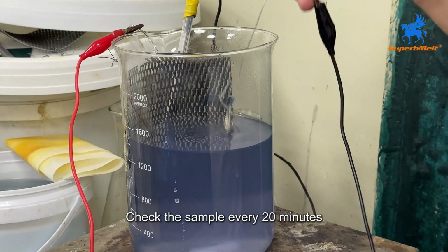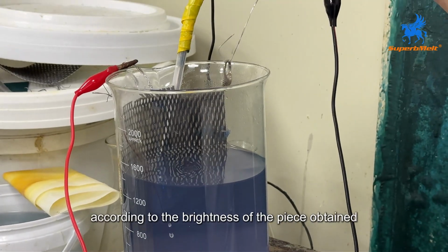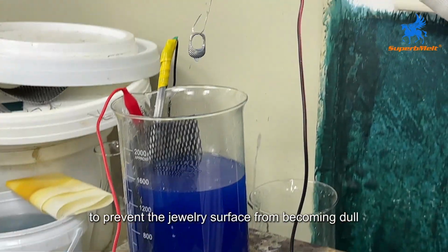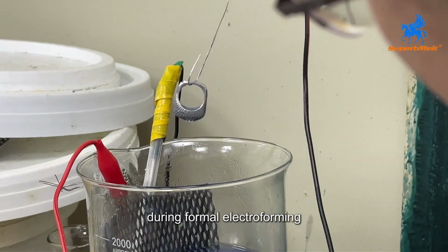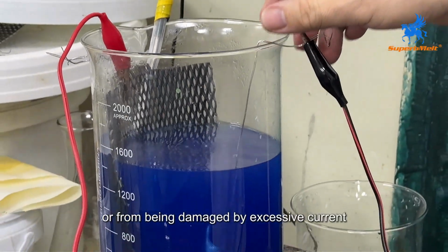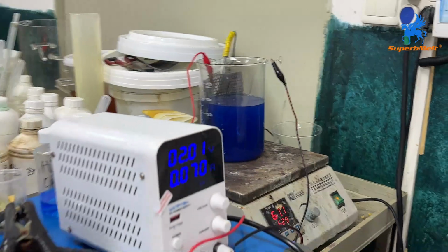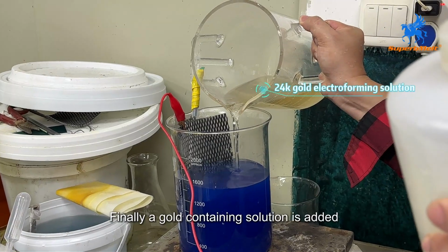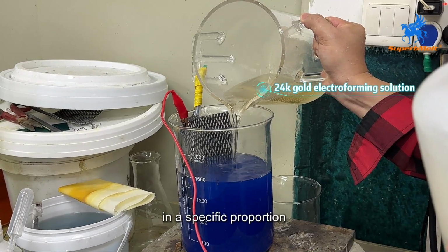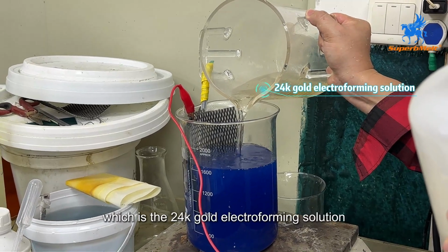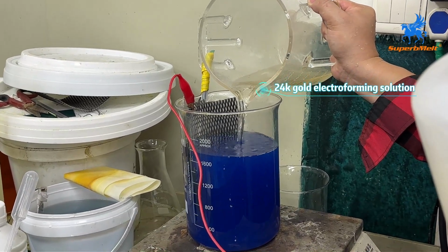Check the sample every 20 minutes and adjust the current according to the brightness of the piece obtained, to prevent the jewelry surface from becoming dull during formal electroforming, or from being damaged by excessive current. Finally, a gold-containing solution is added in a specific proportion, which is the 24K gold electroforming solution.